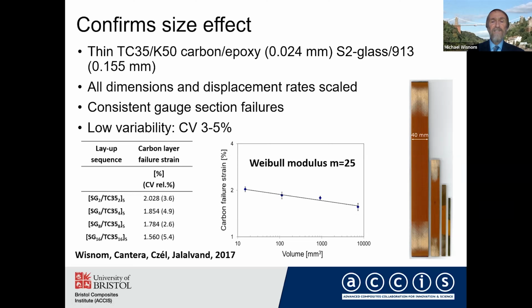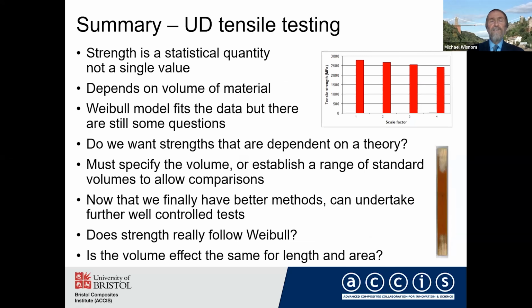Actually, I think that these tests here, where we can be really sure that we've eliminated the failure at the grips, and really have got gauge section failures, confirm really that we have a size effect in these materials. So to summarize on the UD tensile testing, strength is a statistical quantity. You get a distribution of strength really, rather than a single value. And therefore, it depends on the volume of material that you test.